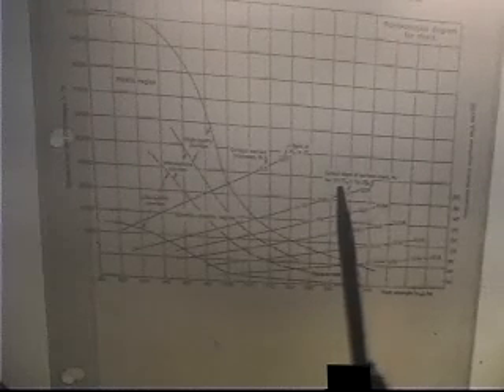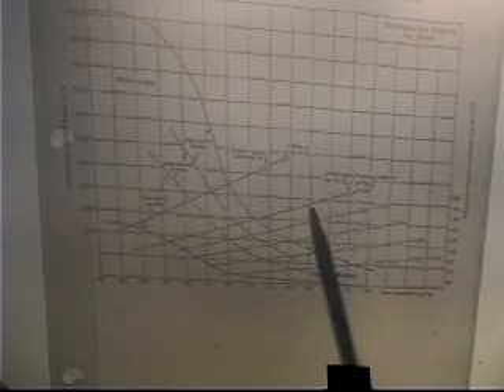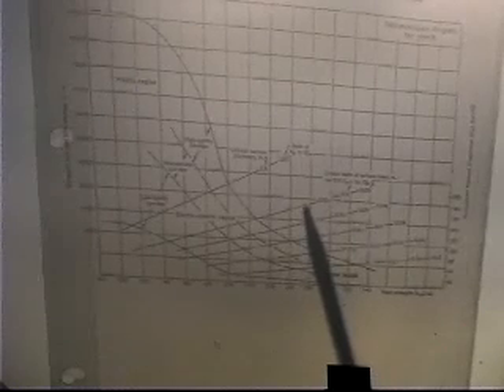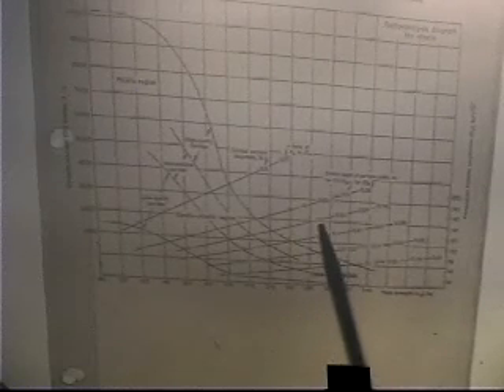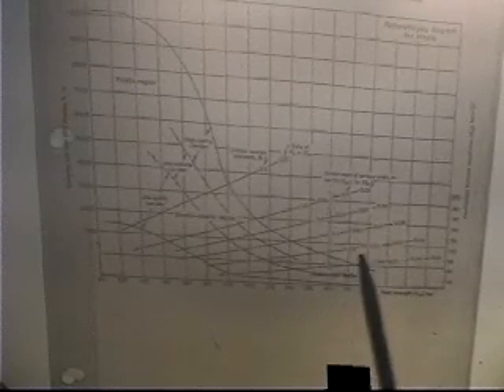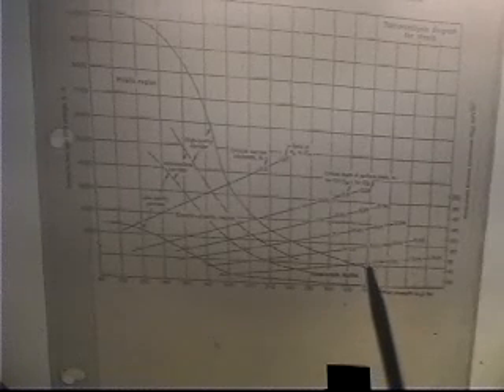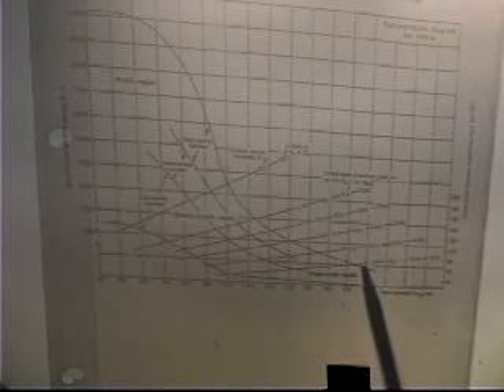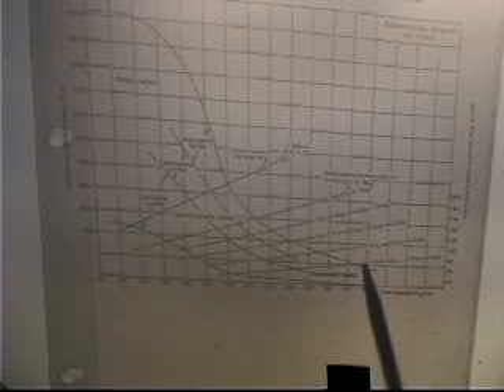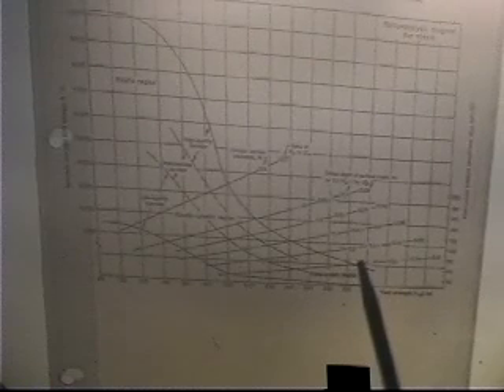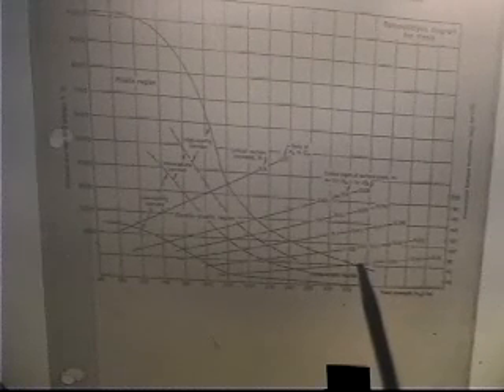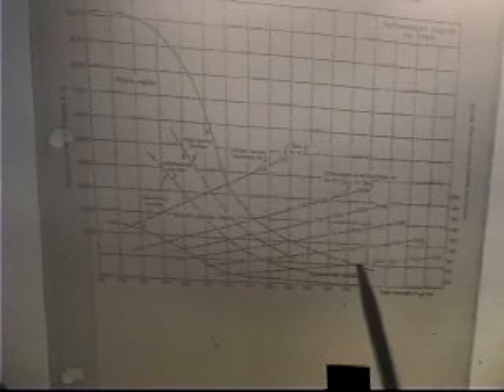If you go to different strengths, you could have critical flaw sizes here, critical section thicknesses at higher strengths of 1 inch, 0.6 of an inch, 0.2 of an inch. If you get to really high strength steels, 1/10 of an inch is a critical flaw size. Now you have to understand, if this was a ceramic, we'd be talking about critical flaw sizes that are less than a human hair, not 1/10 of an inch, because the fracture toughness of a ceramic is significantly less. So this is a fracture analysis diagram, and you can go back and you can do the fracture mechanics and figure out all kinds of wonderful things.